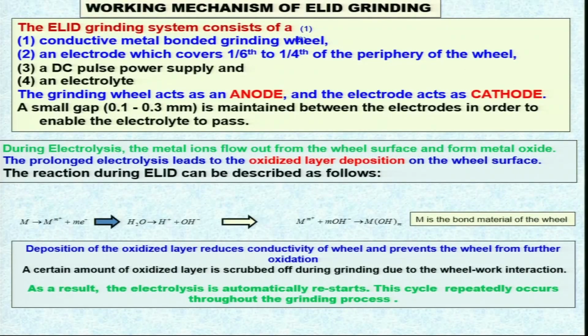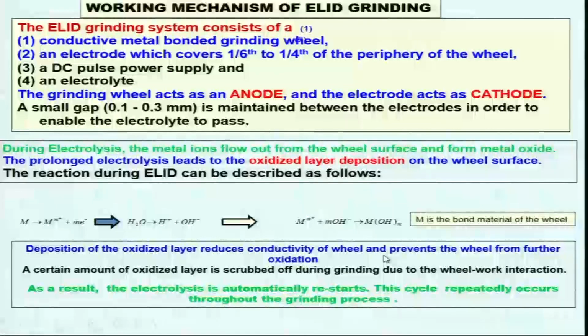Deposition of the oxidized layer reduces conductivity of the wheel, because the oxidized layer is partially conducting or non-conducting, and that is why the conductivity of the grinding wheel reduces. I am saying partially because in certain compositions this may be partially conducting, but in most of the cases it is electrically non-conducting. So, it reduces conductivity of the wheel and prevents the wheel from further oxidation, because electrolyte cannot directly contact the bonding material, that is copper or some other material, because in between the oxide layer is there.